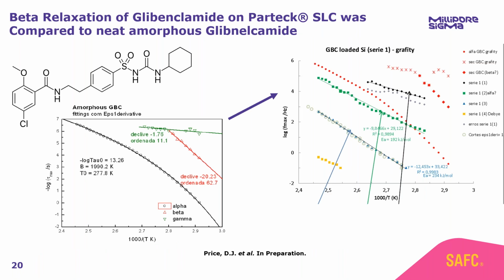So what's happening to glibenclamide within this 6 nanometer pore is identical to what happened to menthol. I'm not going to spend too much time digging into what these graphs show, so I'm just going to tell you the main conclusions. On the left-hand side, we have neat amorphous glibenclamide. That means glibenclamide without any kind of stabilization. And what you can see with the black line here is a very, very prominent alpha relaxation event, and also a very prominent beta relaxation event.